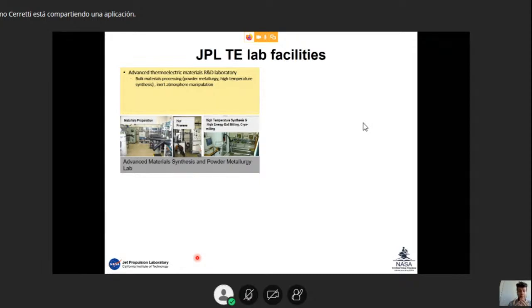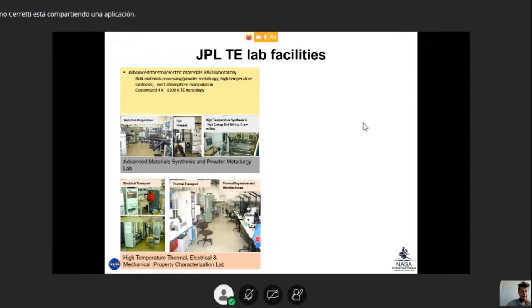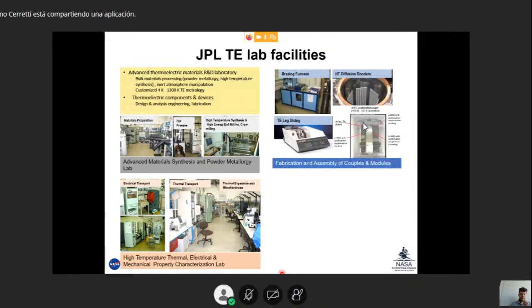We prepare material mixtures. We do the synthesis of them. We press them. We then generate discs and pellets that are used for the characterization. We characterize the electronic, thermal, and mechanical properties of the material, which need to be all consistent over time. After that, we have the components and device lab, where we have brazing furnaces, diffusion bonders,